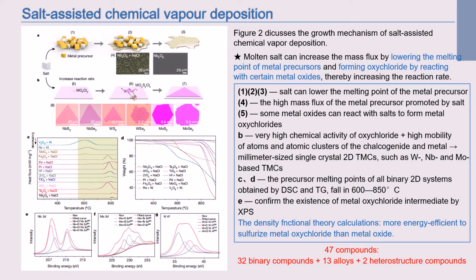In addition to the lower melting point, figure 2b shows that some metal oxides can react with salts to form metal oxychlorides, which evaporate at an appropriate temperature to promote the growth of 2D TMCs. And according to TG and DSC measurements, the precursor melting points of all binary 2D systems fell within the temperature window of 600 to 850 Celsius, as shown in 2C and 2D, which matches the temperature range of the target material growth.